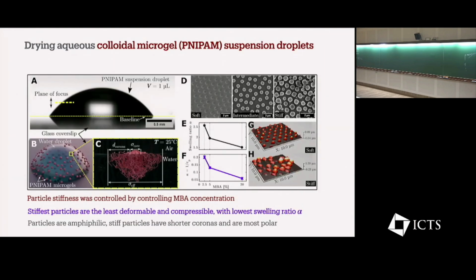So, we make these colloidal particles called microgels in our laboratories. Microgels are like these 500 nanometer rasgullas that are made entirely of this polymer called poly-N isopropyl acrylamide. The reason why I call them rasgullas is because these are very porous, it's basically a mishmash, a ball of polymers, and when you put them in water, they absorb the water because of an interaction between the amide group in this p-NiPAM and the water.